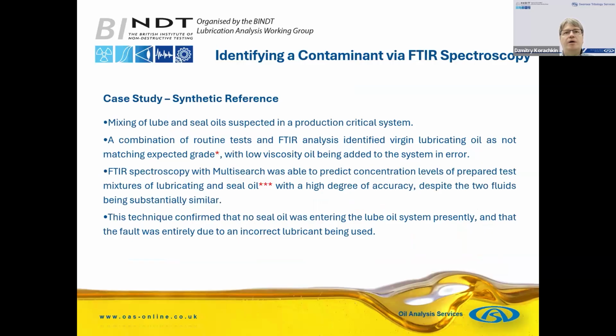Another case study, we had suspicion of seal oil getting into the lubricating oil. We performed infrared analysis, some other tests, and they provided us a sample of virgin oil. And we found that the virgin oil sample they provided us was not matching the expected grade. And that's why the viscosity was different. So we used infrared spectroscopy as well to check the concentration levels of prepared test mixtures of lubricating and seal oil. We were able to predict it with a high degree of accuracy, and we were able to confirm that actually there was no seal oil in the lube oil, and that the fault was entirely due to an incorrect lubricant being used.